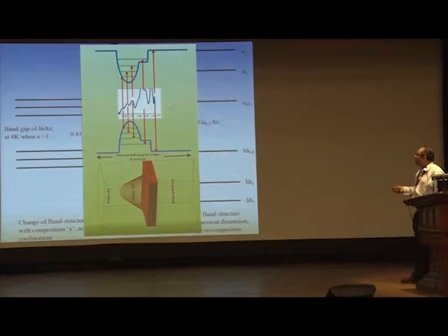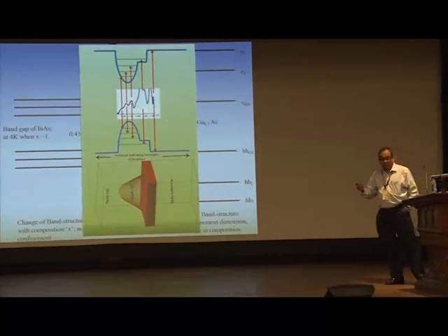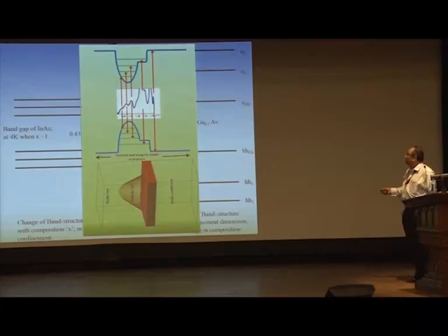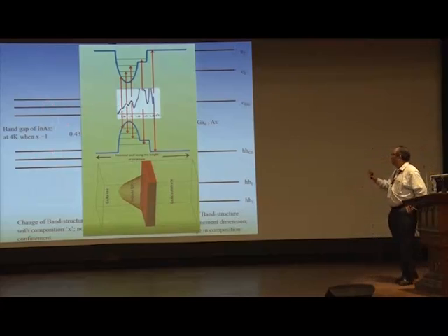Essentially, if you are measuring the separation between these peaks in PL, you can directly measure the effect of size and also the shape. But the absolute position of this PL peak depends on the band gap. So all these parameters will help you to understand how things are working.